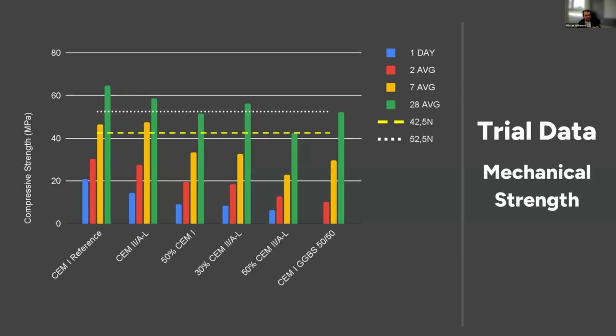We then started to look into replacement of CEM2s, where we also had limestone filler in the mix. So really, that's where you start to maximize your carbon benefit there with that blend of calcined clay and the limestone filler. Again, seeing very similar properties with 30% CEM2 replacement. Clinker contents were quite similar, but what we're actually seeing was a better late strength and pushing us up into the higher strength classes.